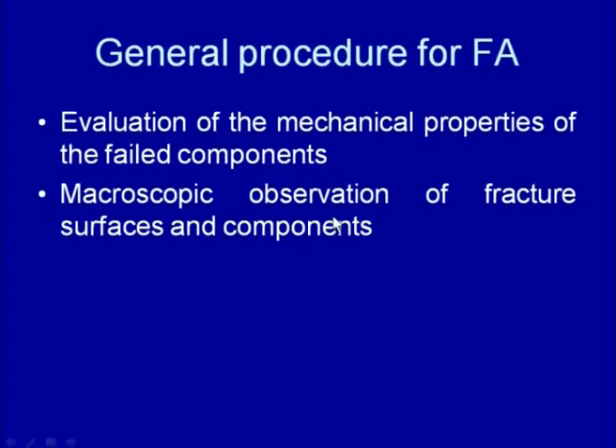not by microscopy. So the macroscopic observation will give an idea about the stress state under which failure has taken place, the location from where failure has taken place, the fracture initiation site, and the direction in which the crack has propagated. So this information cannot be observed using microscopy. Only macroscopy can give us this vital information. Or if something else is present like paint or oil, or some oxidation is observed on the fracture surface, then it will indicate how long ago the crack was initiated, which might have contributed towards the failure.